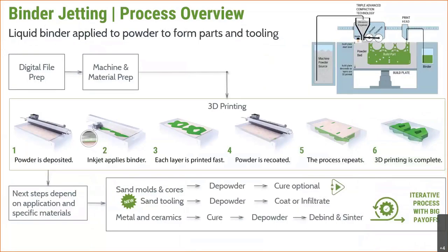Now, the binder jetting process is the same through all technologies as far as laying down a thin layer of powder and then coming by with a print head and depositing that binder onto the powder. And wherever that binder adheres to the powder, you form what's called a green part. Then you do that process, rinse and repeat over and over again, laying a thin layer of powder, spreading it, compacting it, and then ink jetting onto that what your bitmap of your CAD file is. You do that however many layers are in the build, and then you have a green part that is ready for the next step in the process, and that is curing.